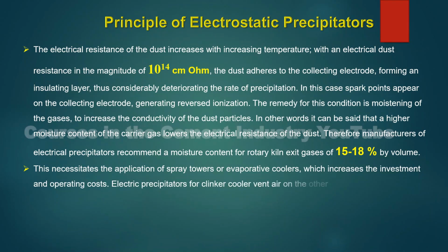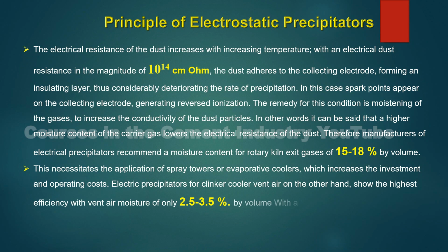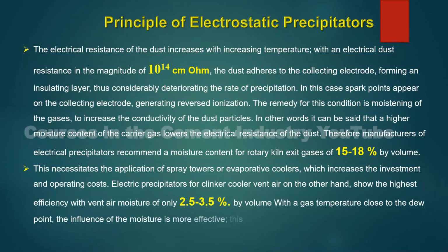Electric precipitators for clinker cooler vent air, on the other hand, show the highest efficiency with vent air moisture of only 2.5 to 3.5% by volume. With a gas temperature close to the dew point, the influence of the moisture is more effective. This results in a better degree of precipitation.